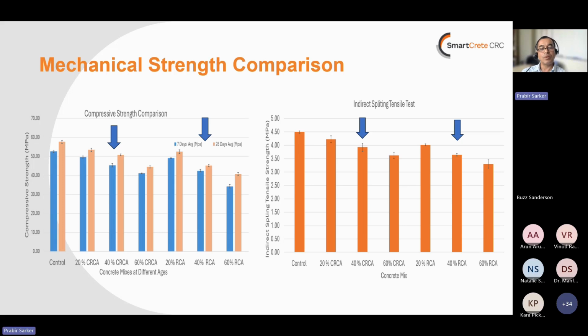For 40% C&D waste aggregate, we got even more reduction in compressive strength. With the increase of CRCA or C&D waste aggregate, in both cases, we can see a decrease in the compressive strength. That's normally what we can expect. The indirect tensile strength followed the same trend as the compressive strength of concrete mixtures using either CRCA or recycled C&D waste aggregate.